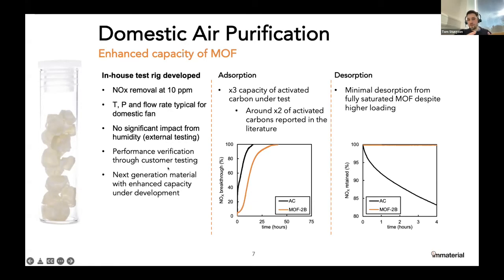The gas stream that we used didn't have any humidity, but we did do external testing with humidity, again, for the same activated carbon and the same metal organic framework, and saw essentially the same performance. So humidity doesn't seem to have an impact. And then we're working with some of the leading providers of these sorts of fans in the UK and Europe, and the test data that they've shared with us from the materials that we've sent to them is again backing up what we're seeing with our internal testing.